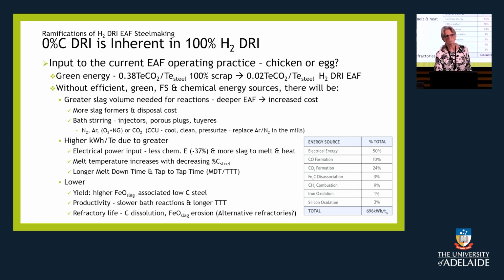You're going to have to put in more slag formers to deal with the gangue. That's going to increase your cost, not only for the slag formers, but also for removing the slag and disposing of it. You're going to have no bath stirring, so higher kilowatt hours because of that. You're going to have to physically put in some kind of stirring mechanism in the arc furnaces to enable the reactions to occur. You're going to have much higher kilowatt hours due to the greater electrical power input that you're going to need to heat the slag, which will be twice the volume.